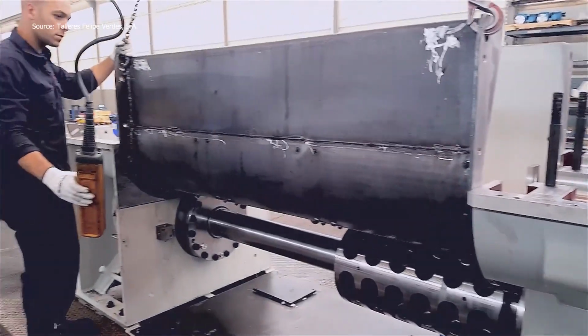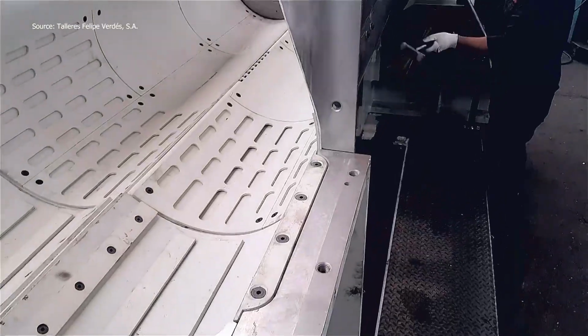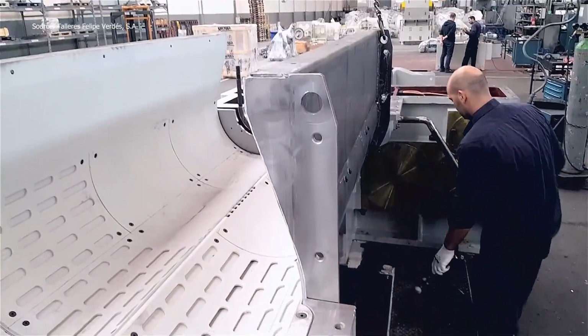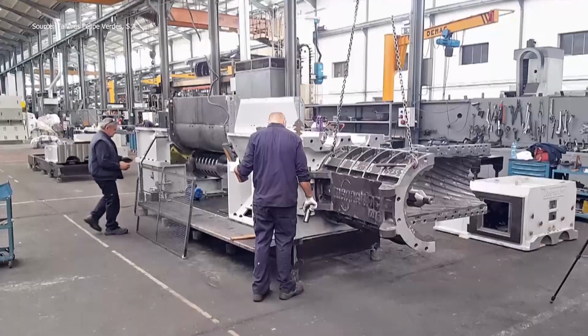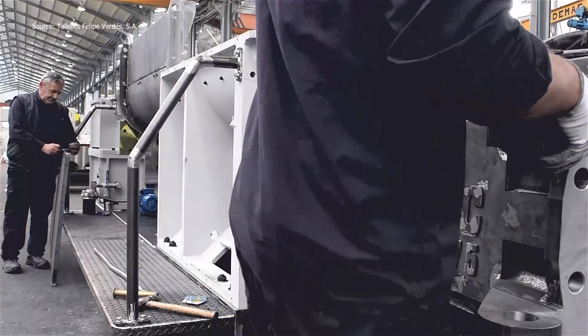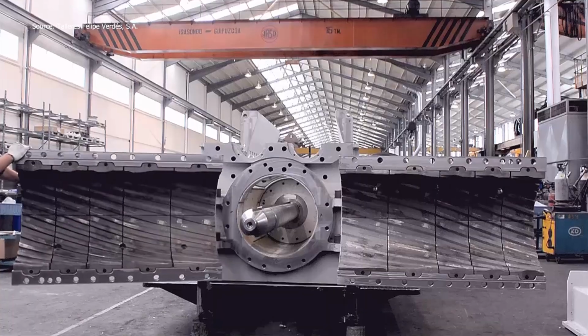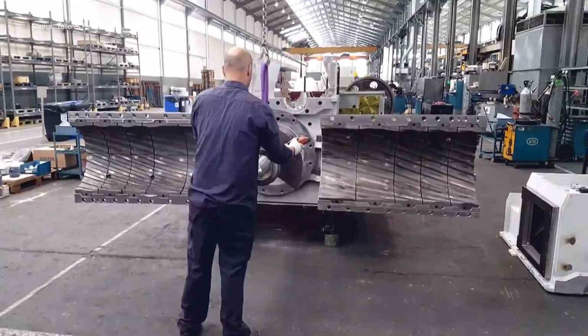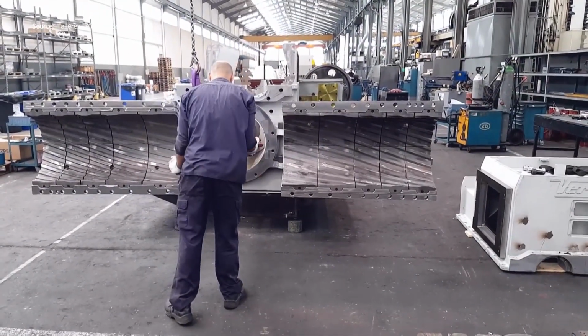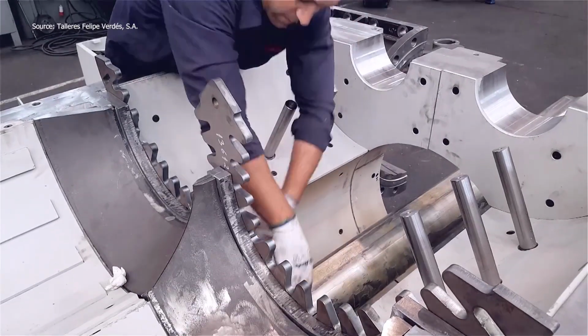A vacuum chamber located above the extrusion barrel removes air pockets before shaping. The chamber has been enlarged compared to previous designs, significantly improving de-airing efficiency and resulting in higher density, more stable extrusions. The screw mechanism, powered by a frequency-regulated motor, moves the material forward. Helical gears with dual-shaft transmission provide consistent torque and allow the machine to handle high loads during continuous operation. The interior is lined with wear-resistant components to extend service intervals.